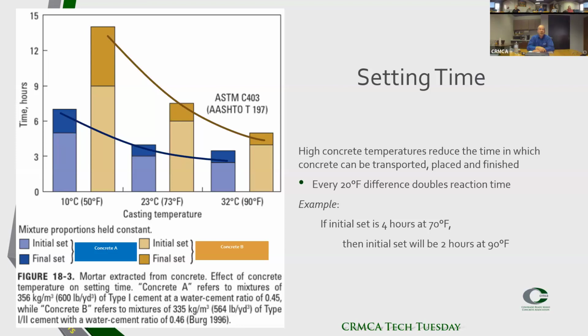So let's say if you have an initial set of 4 hours at 70, the initial set will be 2 hours at 90 degrees. So you see there's that window for the finishability really shrinks a lot. That's something we need to consider. If we go from 70 to 50, then very likely the initial set will be around 8 hours.